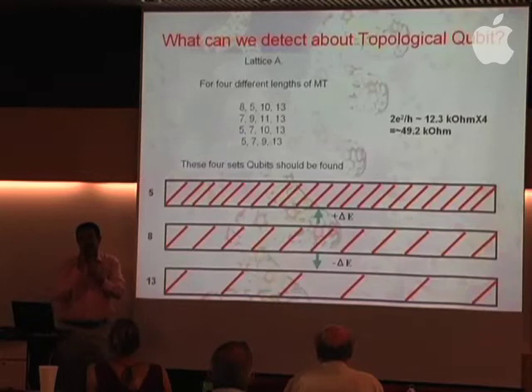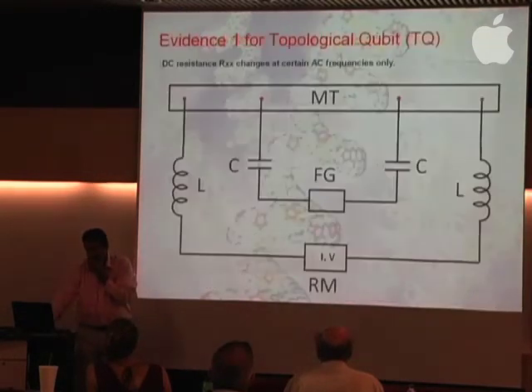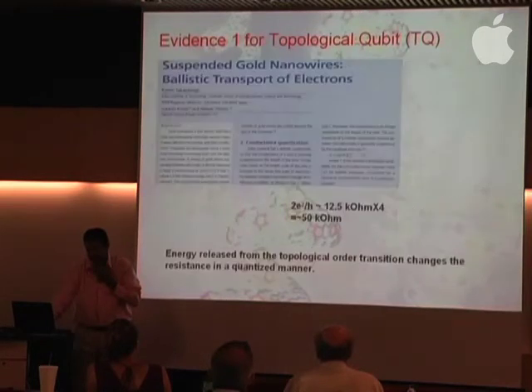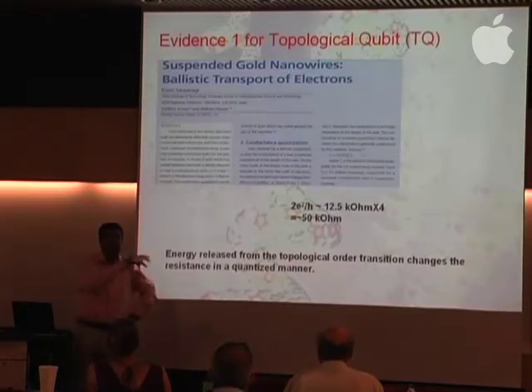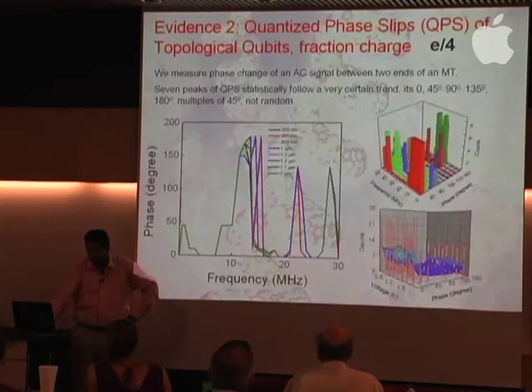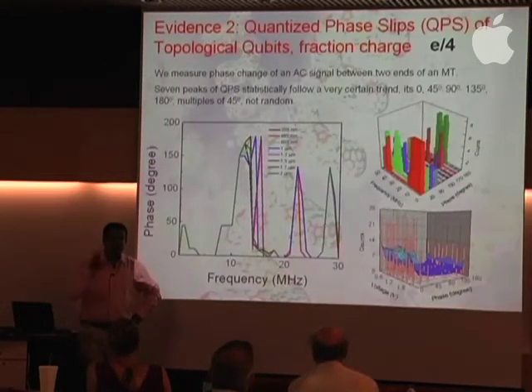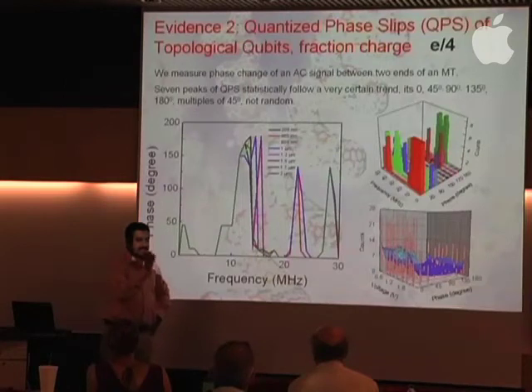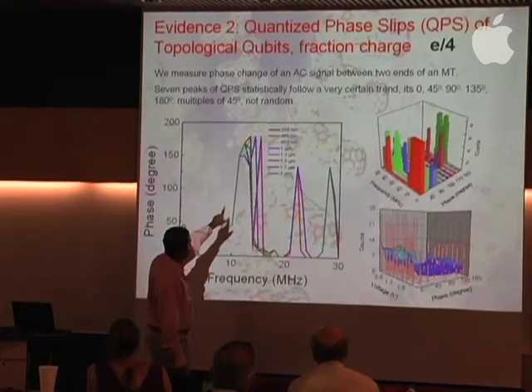So that means we are probably in such a situation where we are really seeing some kind of quantum mechanical effect. And the resistance is also around 48 or 50 kilo-ohms. So we can say how many channels are operating, or quantum mechanically what the situation is out there. We measure the phase. One of the very interesting things is that if there is a topological qubit, and if you measure phase, then there should always be some quantized phase associated with every single peak. And we measure that for different lengths, how the phases are occurring.